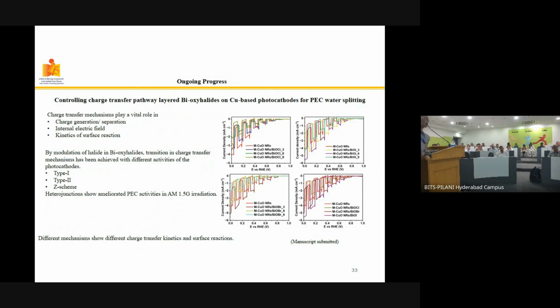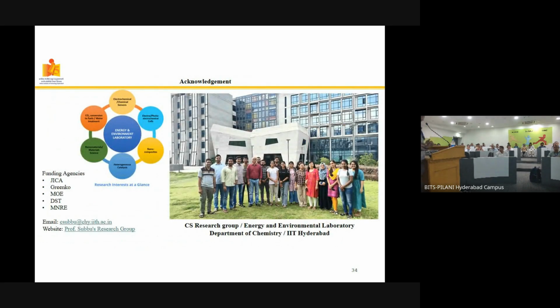Once again, if you take the recipe, it is a copper-based P-type material. We are going to retain that, but the only thing is that there is a 45% decrease in activity after 6-7 hours, because even though whatever I said has been published, finally there is a degradation of the material. To prevent that, this oxyhalide combination is something we are working on right now. The observations will of course be communicated.